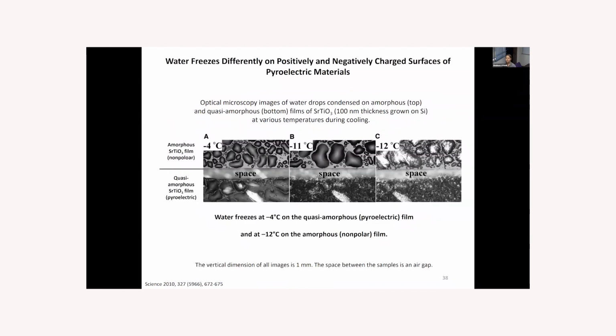It has also been seen on the STO films, by comparing the non-polar and pyroelectric crystal, that the water freezes preferentially on the positively charged surfaces. And this was shown experimentally in this work here. As you can see here, for example, water freezes at -4 degrees C on the pyroelectric film and at -12 in the nonpolar film, which is a big difference of temperature for water freezing.